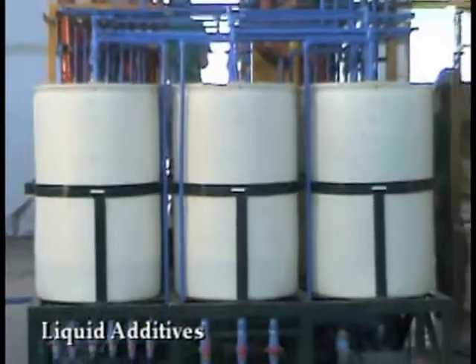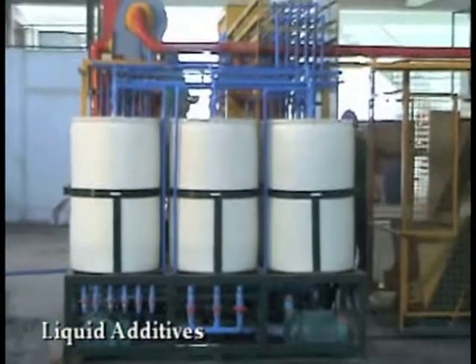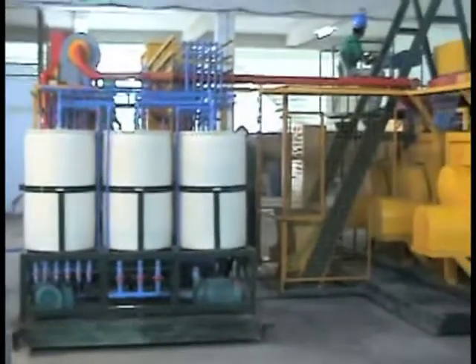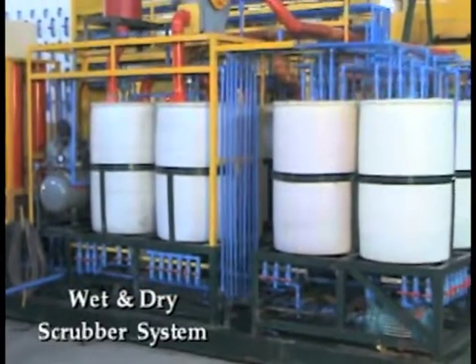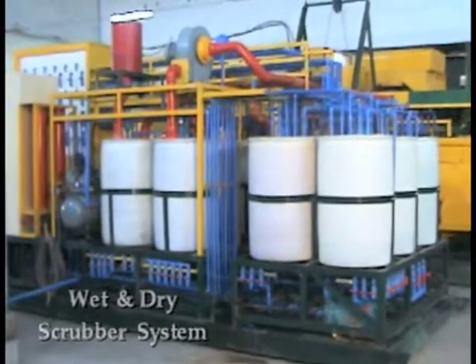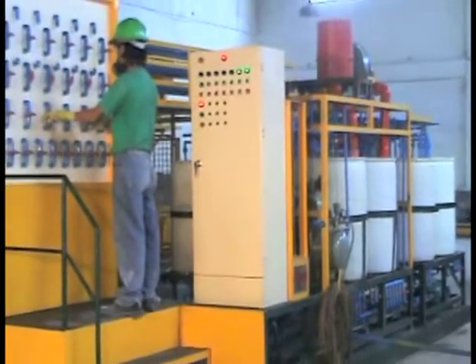The non-organic waste with a particle size of between 12 to 15 millimetres is conveyed into the mixing tanks where proprietary liquid additives are introduced. These chemicals render the waste non-toxic and inert and produce a thoroughly blended homogenized amalgam. At this stage, wet and dry scrubbers effectively remove all dust and gases produced during the mixing, and ozone is generated and added to eliminate any foul odours which may remain.